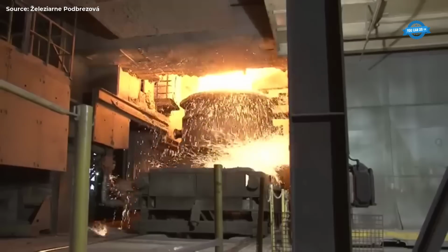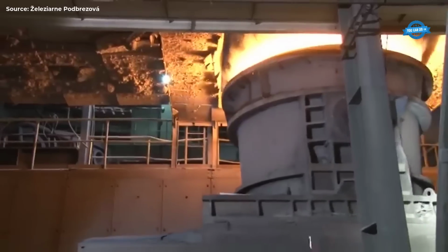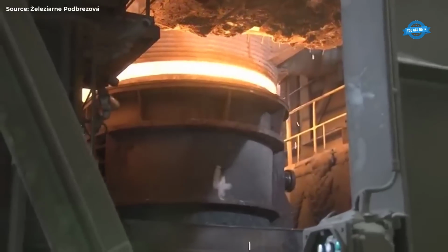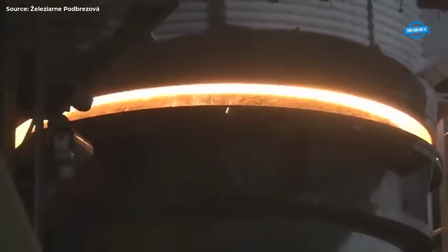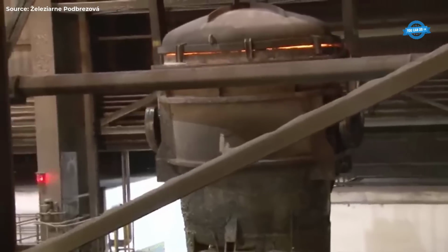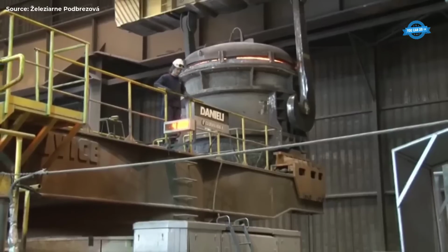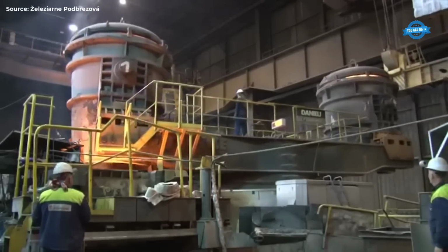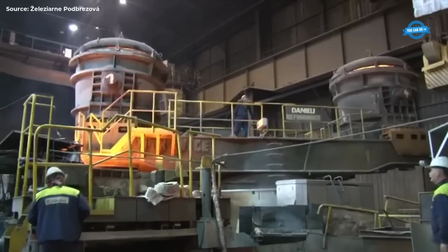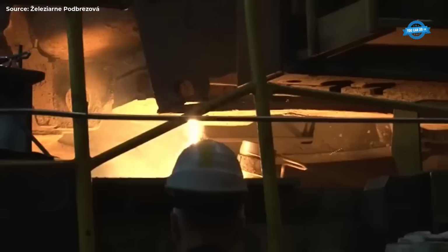At the heart of the mill is an electric arc furnace capable of melting up to 60 tons of scrap per hour at a temperature reaching 1620 degrees Celsius. The liquid steel is then transferred to a ladle, where primary alloying takes place during the tapping process. Additional alloying elements are added in the ladle furnace to achieve the desired steel quality.